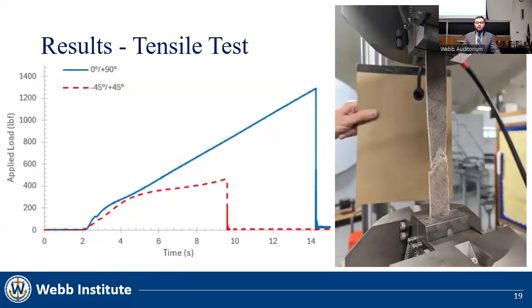The results of the physical tensile test can be seen here. The results are displayed as an applied load over time. The 0-degree fiber orientation, shown in blue, has little plastic deformation and a much higher breaking stress, while the 45-degree fiber orientation, shown in red, has much more plastic deformation and a lower breaking stress. This is due to the lack of continuous fibers and the lower strength of the matrix in the 45-degree fiber orientation.